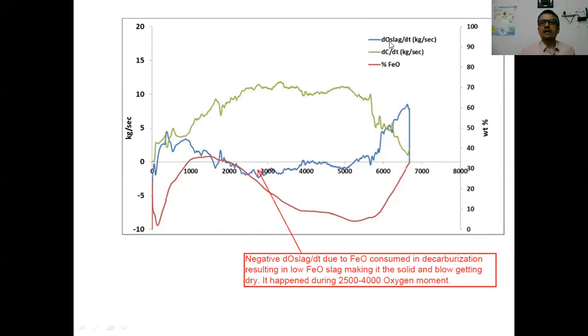Similarly, dO/dt, that means slag oxygen as a function of time. You can find that in this region there is a negative dO_slag/dt due to FeO consumed in decarburization, resulting in a low FeO level in the slag. Obviously, if you look at the CaO-FeO-SiO2 phase diagram, if the FeO level of the slag goes below a critical level, the slag will get dry, and it will no longer remain in the liquid stage, and then all the problems of dry blow will start. That is a highly undesirable situation.